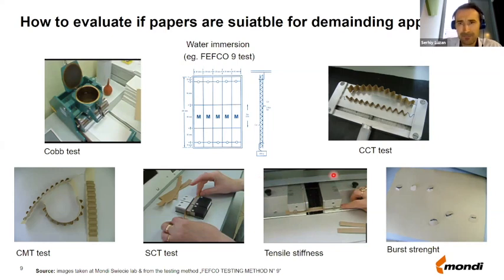Then you have a standard destructive paper strength test, such as the CCT test for fluting, or CMT test for fluting, or SCT compression test for liner, tensile stiffness test for liner, or bursting strength. So these are quite standard tests, and normally you can do them at standard humidity conditions, 50% relative humidity, but also some people use a high humidity condition, so they condition the paper at 90% relative humidity, and then afterwards they perform these tests, and they see how big is the drop in the values of the strength after conditioning at 90% relative humidity. And we will speak about it in a little bit more detail on the further slides.